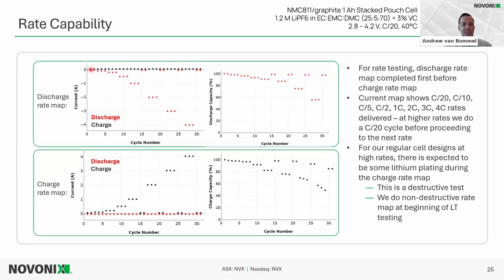3C, so it starts at C/20, then C/10, C/5, C/2, 1C, 2C, 3C, 4C. In between those higher rate steps, we do a slower rate step. So C/20 discharge here, and then go back to 2C, then C/20, 2 C/20s, then 3C, 2 C/20s, and then 4C. And then we see the resultant normalized discharge capacity.